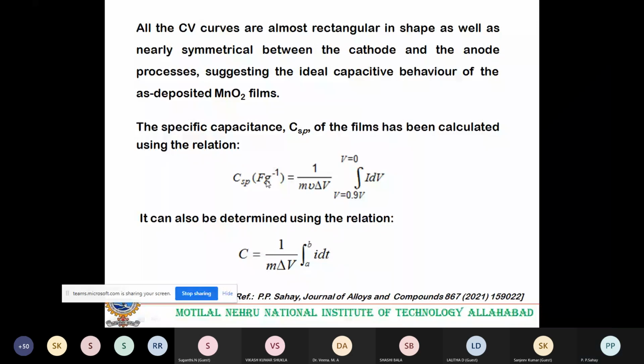What is m? That is the mass of the electrode material, active material you can say. What is the small v? This is the scan rate, that is millivolt per second. Here we have taken it in millivolt. Delta V, this is the potential window. And this is your I, that is current during discharge. And since you are telling discharge, that is from 0.9 volt to 0.